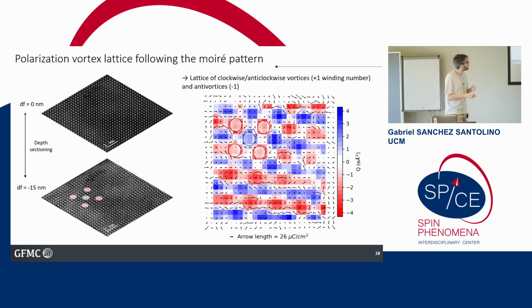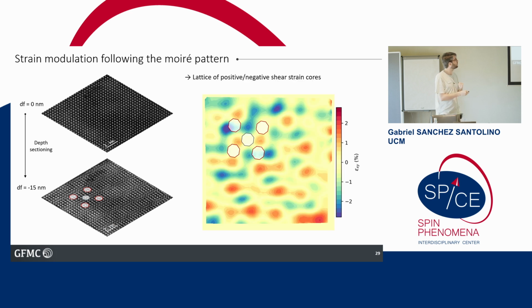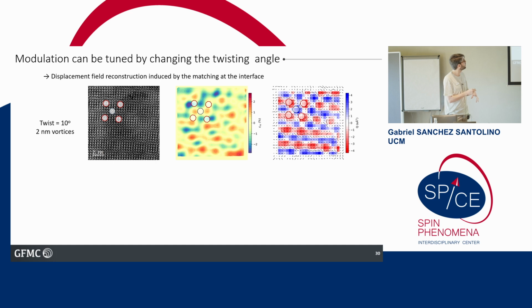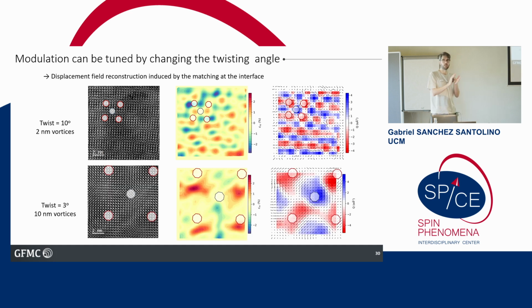So the vortices are aligned with this AA and this AB region, where we have the coincidence of barium over barium or barium over titanium, and in the middle, where we have the biggest deformation of the lattice, the biggest mismatch between the two lattices, we have these positive and negative shear strain cores. And this is how it looks all together. As we are just transferring these two materials and twisting between two different layers, we can select the angle, so we can create these topological ferroelectric structures with the size we want.